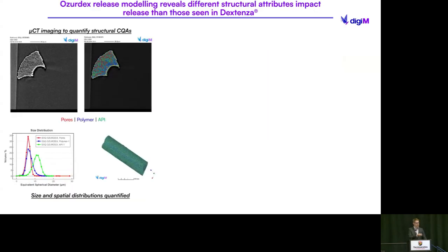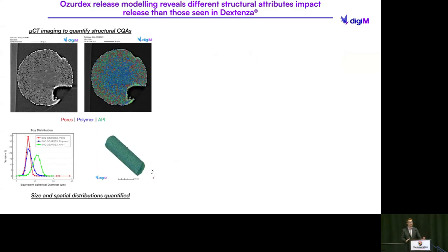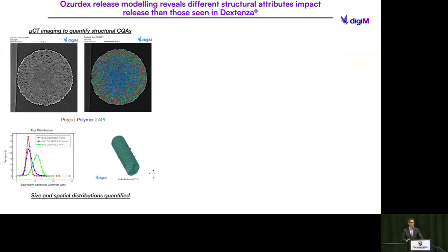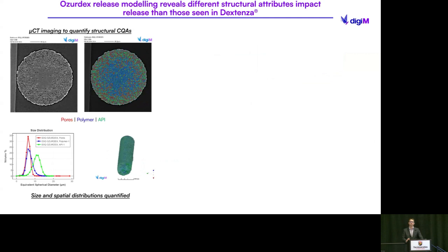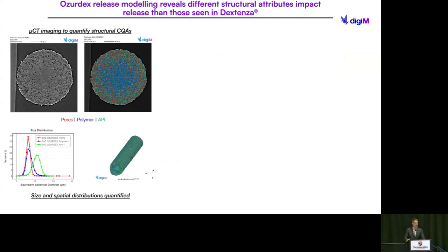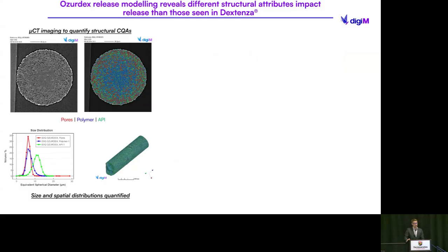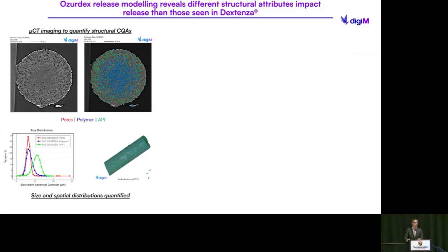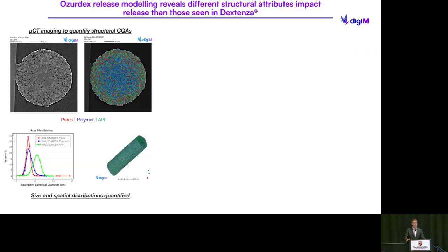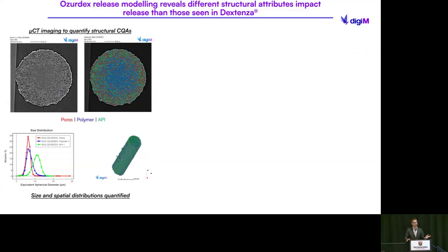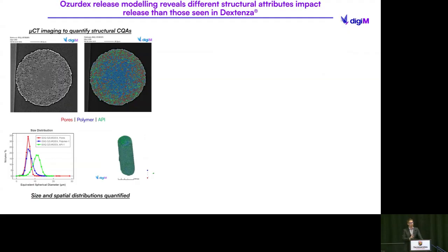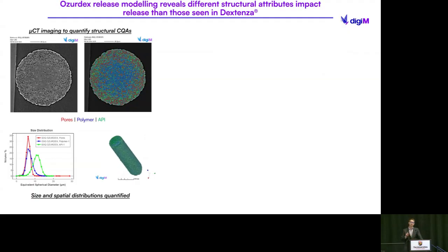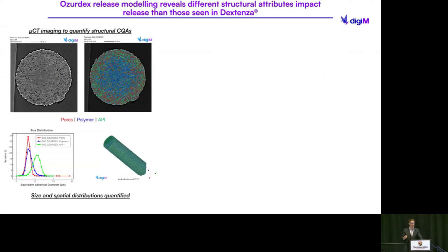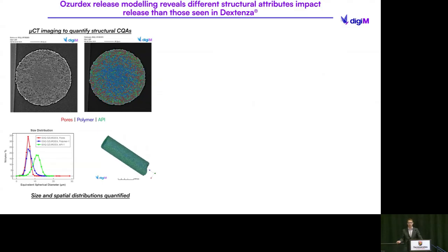So in the case of Ozurdex here, I'm just looking at the RLD because this is already a host of information that we can extract. Coleman presented on the differences between the in-house and the RLD, and showed how micro CT can be used to quantify the pores. What we're doing here is not only quantifying the pores, but we're also quantifying what we refer to as the API-rich domain and the polymer-rich domain.